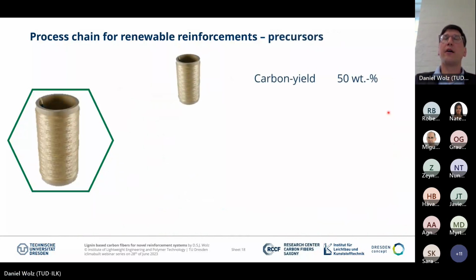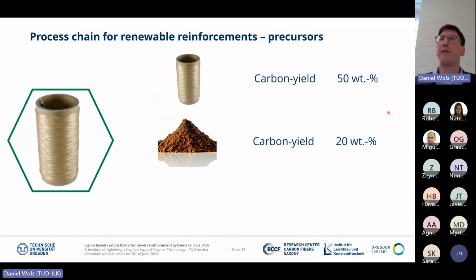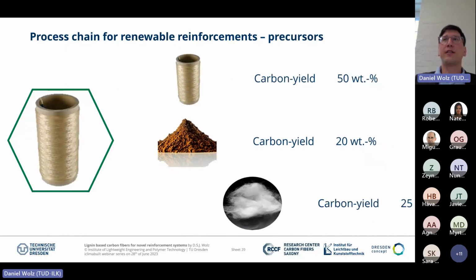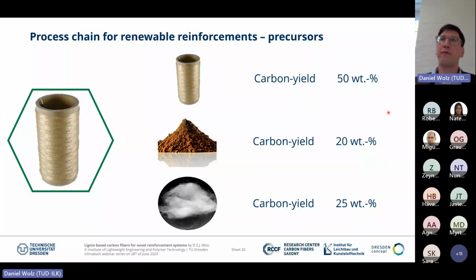So the question is, why is polyacrylonitrile such a nice precursor? Because it has just a carbon yield of 50%. If we are looking at the alternatives as renewables, we have lignin, but these just have a carbon yield of 20%, meaning that we are wasting 80% of the original raw material. Looking at cellulose, it is slightly better, where we have a carbon yield of 25%. Still, it is a decrease in the raw material efficiency.